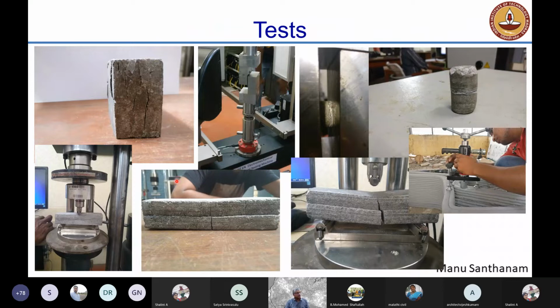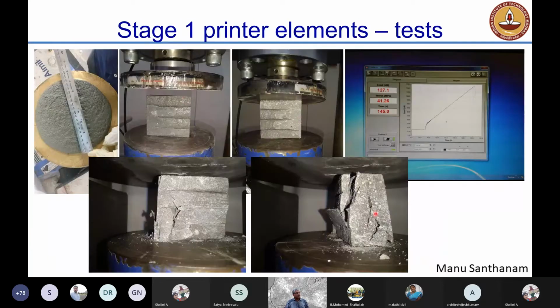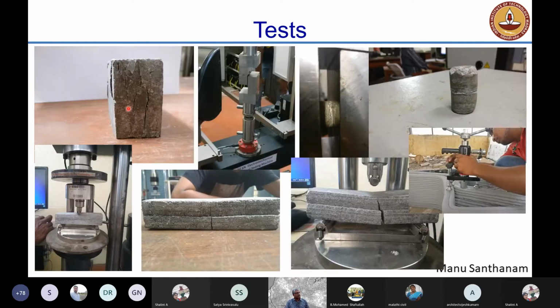So you see here, flexural test is being done for a 2-layered specimen, and you have a proper flexural failure. There's some shifting of this crack at the interface. That means it is moving along the interface to some extent. Here, it's a properly compressed material. You see from the previous picture. Okay, this is the same sort of an object which has been failed in compression.